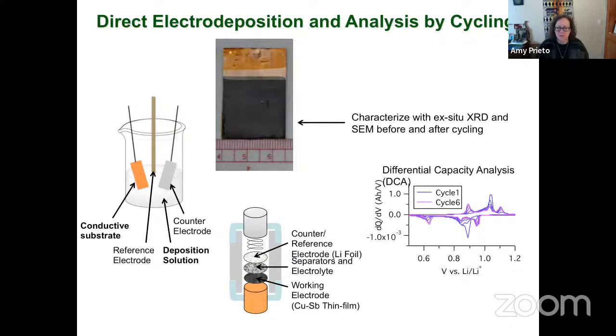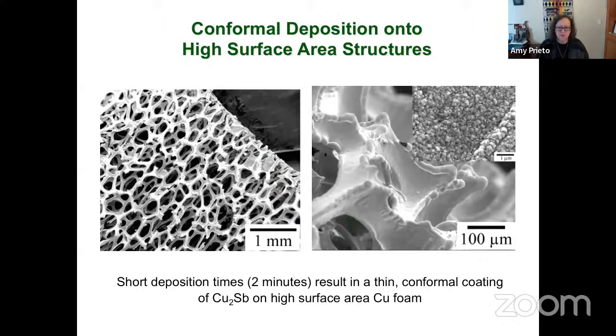And then we typically use differential capacity analysis so that we can look at how the peaks that correspond to distinct chemical reactions evolve over cycle number, over rate performance, changes in electrolyte composition. And this is a really sensitive way of observing changes as a function of various variables. So let me just show you quickly a few pictures.